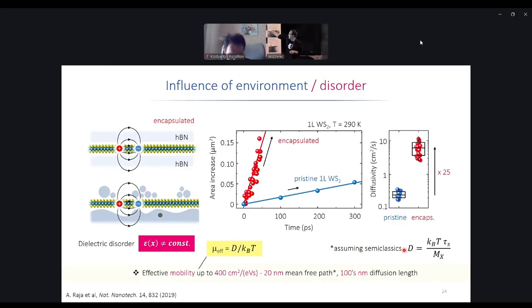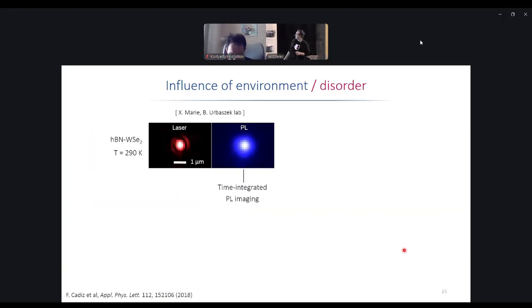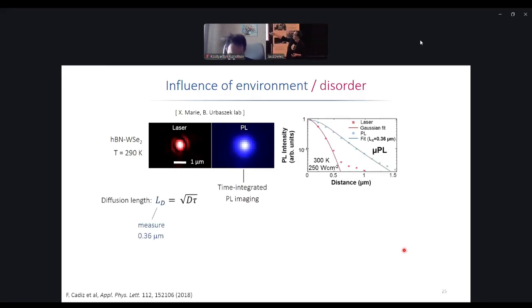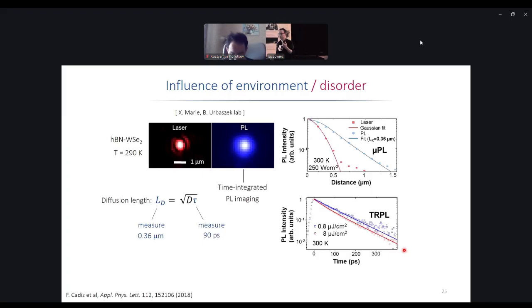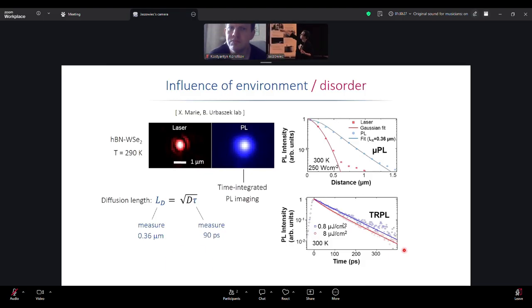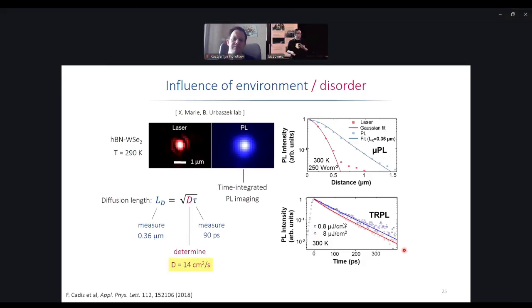And one needs to make some assumptions. One can make some assumptions to get these numbers about the type of transport, and this will also be a topic a bit later on. There is also a version where you do this analysis without time resolution. I'm just showing it to you because this is something that is done quite often without time resolution in the given experiment. What one can do, one can look at PL, measure diffusion length, just see how big your PL spot is, and then perform an additional measurement of the recombination time. Yes, and that will give you the diffusion coefficient. So these are two different experiments, and then you get the diffusion coefficient.